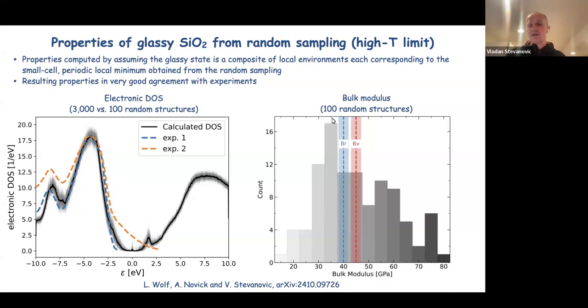So we took a sample of 100 from 3000 randomly, and we calculated the bulk modulus of each one of those. The histogram of bulk moduli is shown in gray, but now the averaging procedure is a little bit complicated. I'm not going to go into the details of it. Basically, you consider our mixture as a composite of local environments represented by each of these 100 structures, and then from the theory of elasticity, you can find